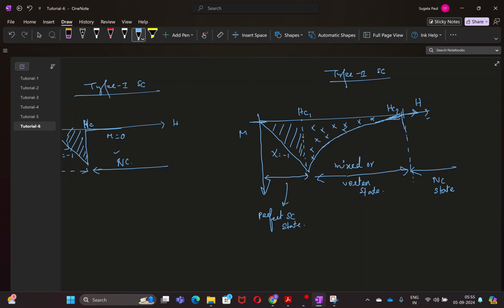So it was repelling any magnetic flux from entering the sample, and that is why you had a perfect diamagnetic situation. But above the Hc1 value, the magnetization does not suddenly go completely down to 0. That means it has not entirely entered the non-magnetic regime, but a finite value of magnetization is still left, which gradually decreases and finally goes to 0 at Hc2.